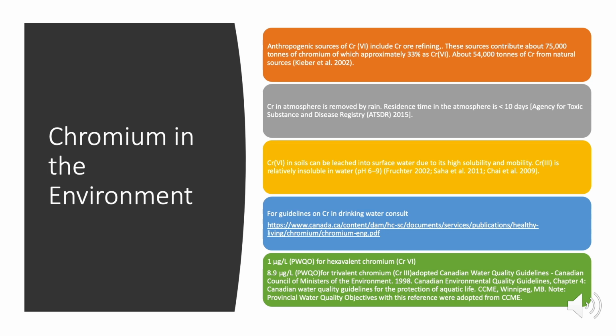Chromium in the environment can come from anthropogenic sources and natural sources. Anthropogenic sources of chromium-6 include chromium ore refining, and these sources contribute about 75,000 tons of chromium, of which approximately 33% are as chromium-6. About 54,000 tons of chromium come from natural sources. Chromium in the atmosphere is removed by rain, and the residence time in the atmosphere is less than 10 days. Chromium-6 in soils can be leached into surface water due to its high solubility and mobility. Chromium-3 is relatively insoluble in water. I included here some Canadian guidelines for chromium in drinking water and the environment, but the take-home message here is that they are either 0 or extremely low levels if it's in the environment.